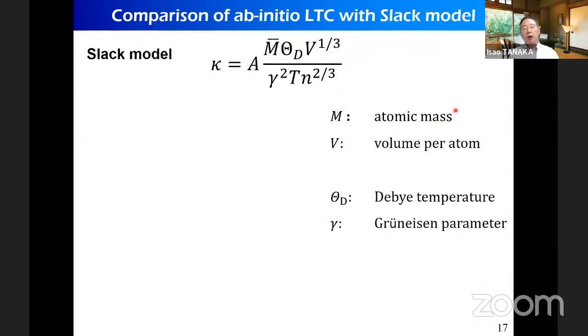If you have a good physical model, then the story is very simple. This is the traditional way that solid-state physicists work. And if you look at an advanced solid-state physics textbook, you can find this model called the Slack model. Based on the Slack model, lattice thermal conductivity is expressed by this equation with Debye temperature, Gruneisen parameter, together with atomic mass and volume per atom. We can compute these quantities by phonon calculation from first principles. So we can compute this quantity.